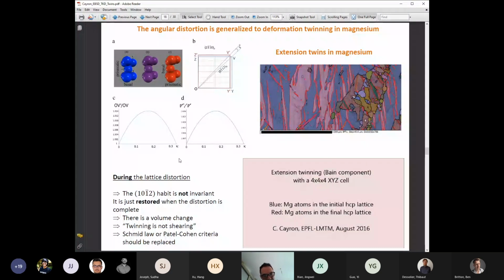What is also interesting is that if you look at the movie, or if you imagine what happens between the start and the end of the extension twinning, you will also realize that there is a change of volume in between. The volume at the end is the same as the volume at the beginning, but in between, there is a slight increase of volume. And you can say, instead of calculating the Schmid factor to determine when the twin will be formed, the condition to form the twin is not the Schmid factor, but the condition to reach the maximum of volume change, because it's like the gap you must cross.